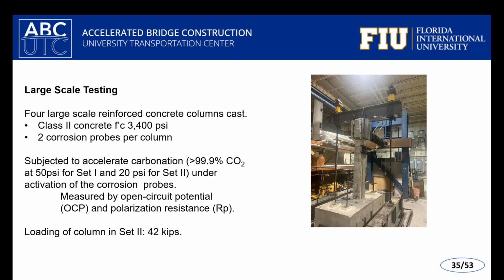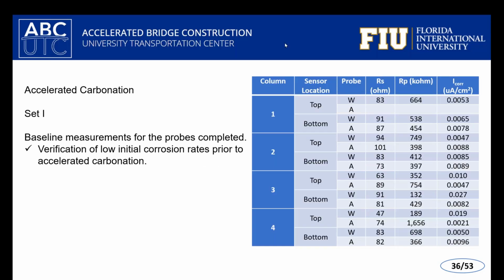The bread and butter for us really is the open circuit potential, the half-cell potential some people call it, and also to look at the polarization resistance relating to the corrosion rate. So before we pressurize the carbonation pressure vessel, we establish our baseline just to make sure they're not corroding up front. So for all of our columns and all our sensors, we measure corrosion rate using the linear polarization resistance method. And in this table, you can see some of the results we have.